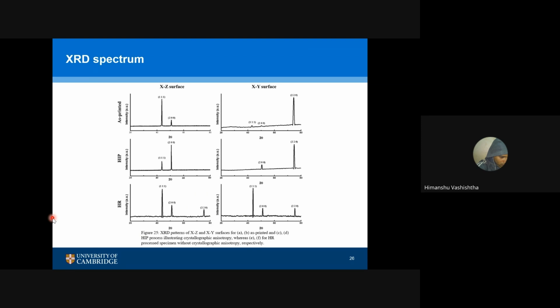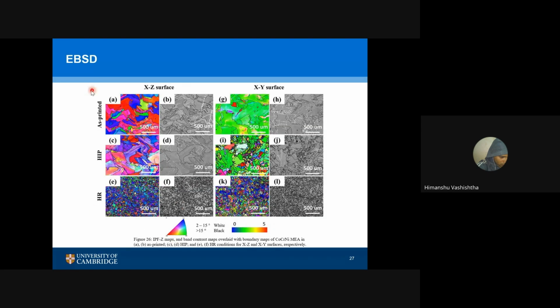Now, to visualize it in a more effective manner, we performed some EBSD measurements. So here you can see it, as as-printed, XZ surface and XY surface, and you see the heterogeneity - that's the green color, a different orientation. Here you can see it, different orientation, this triangle is showing you. So here the orientation is different, and here it's different in case of as-printed.